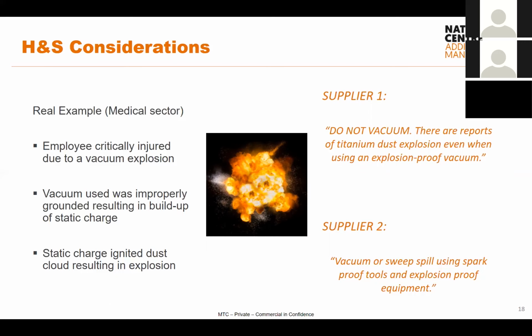So an employee effectively was using a vacuum to clean up a spillage of titanium powder. Now, the vacuum this employee was using was inappropriate for the job. It wasn't grounded properly, and therefore it was able to build up static charge. And then the static charge obviously was enough to ignite a dust cloud of titanium-64, which led to severe injury of the operator in question. Now, in this scenario, you could say they were lucky,